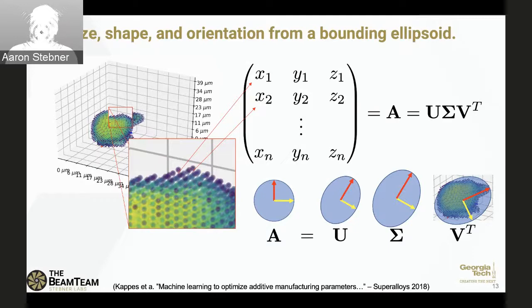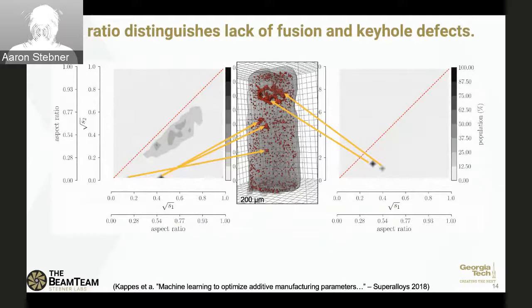We showed that these calculated variables, like the square root of the magnitude of the eigenvectors, or the ratios of the first eigenvector to the second eigenvector, could tell us whether these defects were keyhole-like defects, which are more spherical, so those ratios of the eigenvectors would be more equal, or lack of fusion or crack-like defects, which would be more planar, so eigenvector 1 and 2 would be similar, but 3 would be much smaller, or other things. And so we were able to classify defect types using these matrices without having to visualize and determine visually with a human what types of defects were there. Next slide.